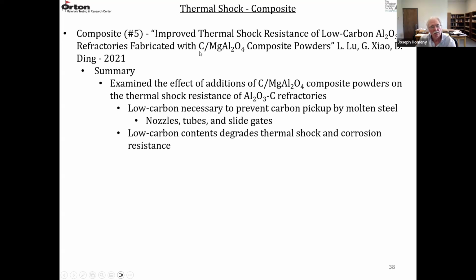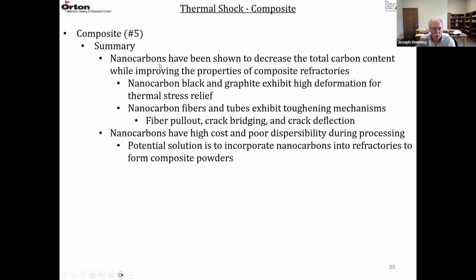So there's been a lot of work recently on nanoparticle additions to refractories. Everybody likes to do research on nanoparticles these days. So the problem with nanoparticles is they're expensive and they're hard to disperse because of the high surface area. But this composite here, carbon MgAl2O4 composite powder, is a carbon nanoparticle in a spinel matrix. So some of the recent work on nanocarbon additions to refractories have shown that you can decrease the total carbon content and still improve the properties of these composite refractories.